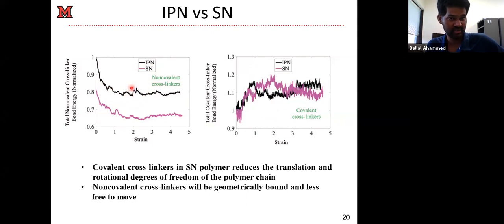I'd like to mention that the cross-linking density for both the SN and the IPN polymer is the same in those two materials. So there is no difference in terms of cross-linking density. They have the same number of crosslinkers in both materials, but we see that the total covalent bond energy for the IPN and SN case is similar, but the non-covalent bond energy is always higher in the IPN in comparison to the SN, although they have the same cross-linking density. So now the question is, what's happening here? What happens to the non-covalent bonds?